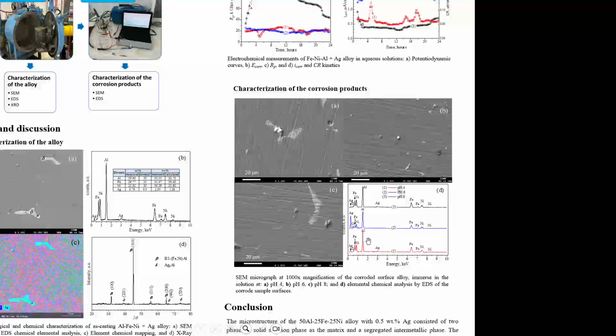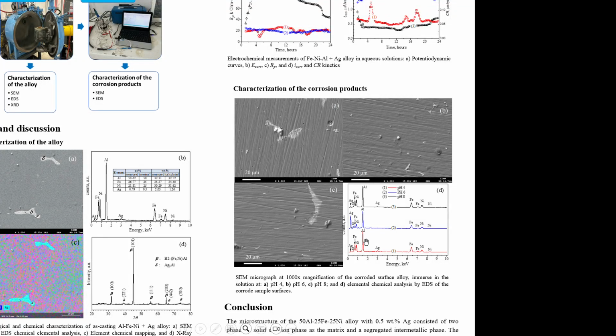The micrograph of the corroded surface of the alloy showed generalized corrosion at all 3 pH levels, and at pH 4 the alloy presents evidence of some pitting. You can see in this picture here. However, most of the current density contribution was associated with uniform corrosion.